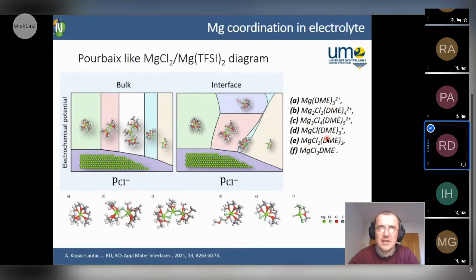And those species are pretty much dependent on the concentration of chlorides that you have inside. So this gives somehow a hint that, of course, there is a possibility that we might also have, for example, magnesium chloride plus, so a monovalent magnesium complex, or even something different, which can also be inserted or coordinated in these organic moieties. But then this picture is even more complicated when you come to the interfaces.